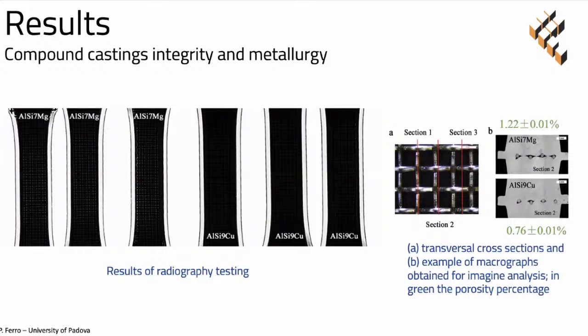These are the main results, in particular the results of radiography testing, that showed a great amount of lack of filling porosity, and in particular a greater amount of lack of filling porosity in the first aluminum alloy compared to the second one. In the first case, we found more or less 1.22% of lack of filling porosity compared to 0.76%. And the difference is due to the difference in silicon content that made the fluidity of the alloy greater in the second alloy.